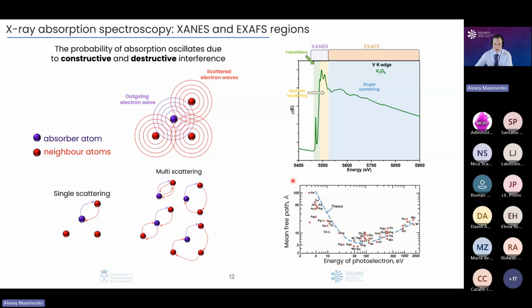What is quite important, here you have the dependence of the mean free path of the photoelectron on its energy. Here we could see that in the range of XANES, when the photoelectron has a very low energy, its mean free path is larger. It means that it could have many multi-scattering paths. Yes, this photoelectron could follow these multi-scattering paths, and that is why in the XANES region we could investigate the coordination symmetry, for example, of our material.